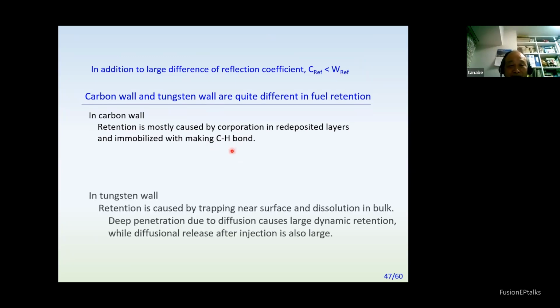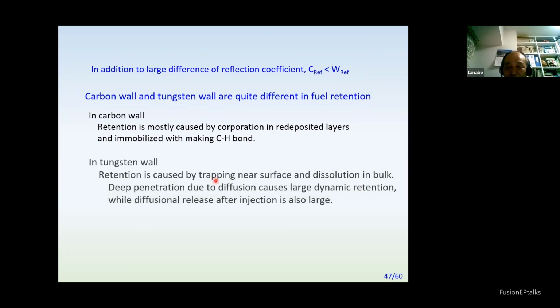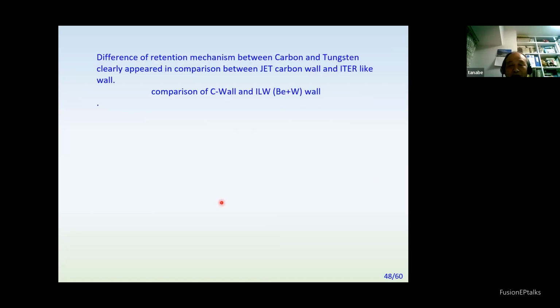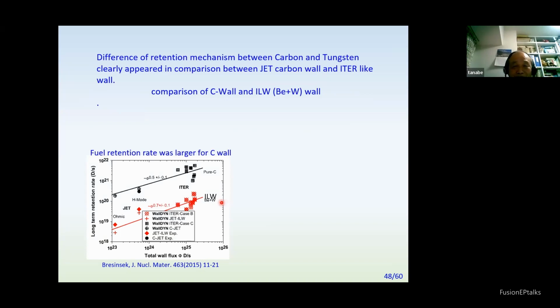But in tungsten, retention is caused by trapping near the surface in addition to solution. So deep penetration occurs in tungsten and diffuses, giving large dynamic retention, but this dynamic retention is recovered by diffusive release after injection stops. This can be clearly seen in the JET comparison of carbon and ITER-like wall experiments. Fuel retention rate in JET compared to the carbon case and ITER-like tungsten case shows two orders of magnitude difference - so the fuel retention in carbon is actually higher.